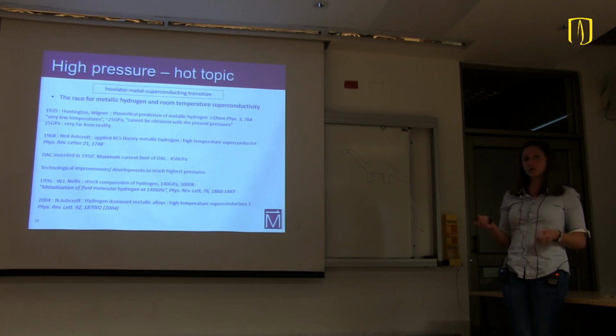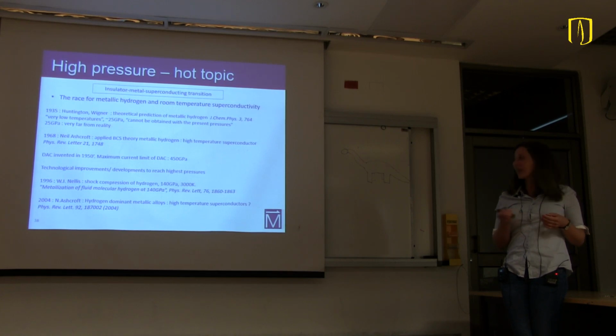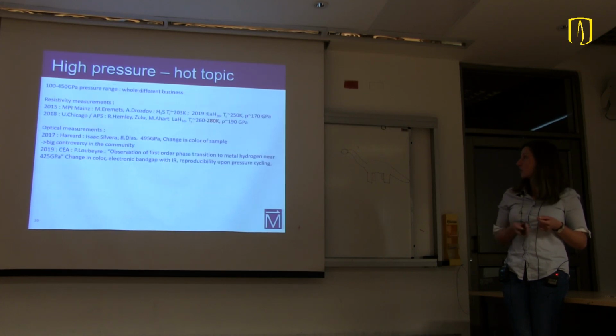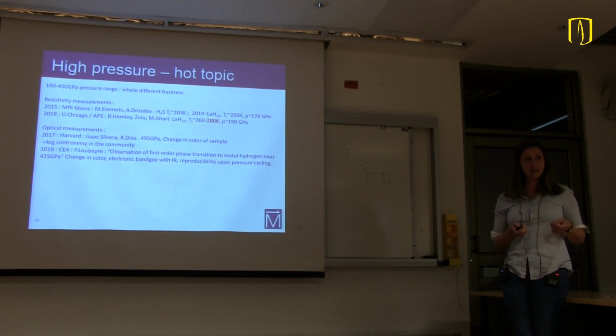And again, Neil Ashcroft kept pushing and pushing the field. And in 2004, he predicted that not only hydrogen, but also hydrogen alloys, hydrogen-dominant metallic alloys, could become very high temperature superconductors, but at pressures lower than metallic hydrogen. That triggered a whole body of work, and it took 10 years of relentless work for high pressure to get to the first result.